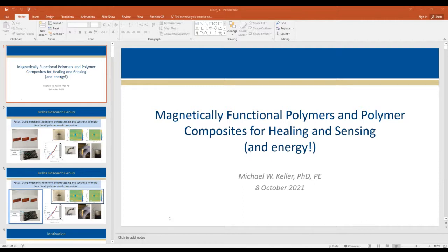All right. So we sort of live in this two space in my lab. This is interesting to me, but I'm not a polymer chemist, so I don't really work in this. But we sort of apply these two techniques. This is the very first self-healing polymer, from around 2002. And this material right here is actually a damage detection system where you can see this cut, and then the color starts changing, and you see this bright red material working there. So I'm going to talk to you a little bit about two approaches that we've done using magnetically functional materials in this space before transitioning to the other.